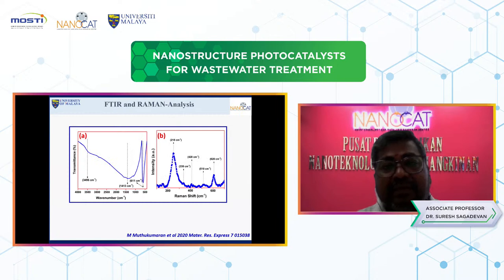And then we did FTIR and FT Raman. From this analysis, we confirm which functional groups are present, like water and any carboxyl groups. As well, we confirm at the lower frequency the wave number at 611 centimeter inverse one, which confirms the copper and oxygen stretching vibrations. This peak indicates the presence of copper and oxygen stretching vibrations, the successful formation of this copper oxide. As well, we did Raman analysis, where different modes of frequencies were obtained. We observed the Raman mode at around 620, about 600 centimeter inverse, which also confirms the copper and oxygen stretching vibrations. So both analyses give evidence for the formation of this copper oxide.